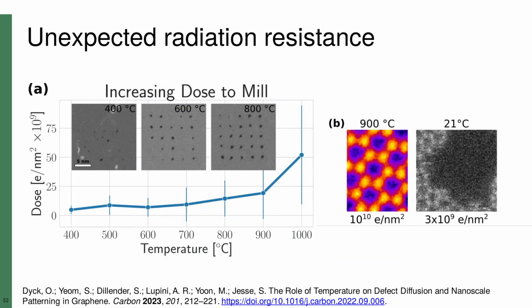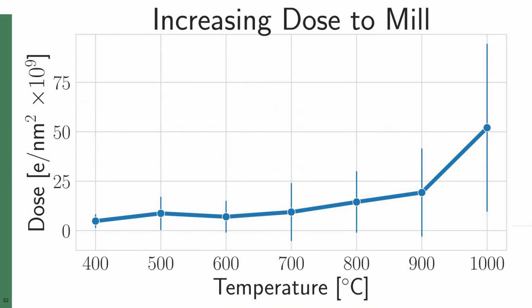We immediately ran into some surprising results. The hotter the graphene, the more dose it took to mill a hole. That's what this plot is showing. We expected that the greater thermal excitation would lead to slightly easier milling, as is predicted by intuition and the most detailed theoretical treatments. What this data shows is that the opposite is happening.